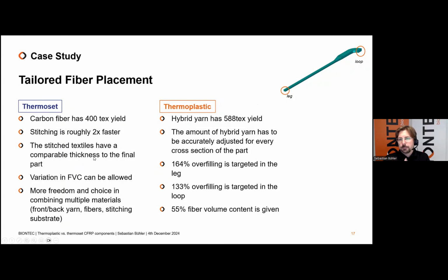And we see that especially for the thermoplastic route, because we bring the thermoplastic matrix directly into the mold and do not inject the resin afterwards, we have to do an overfilling. For the leg section, we had to do an overfilling of 164%, and in the loop, it was only 133%. And the amount of hybrid commingled yarn has to be adjusted very precisely for every cross section in a part.